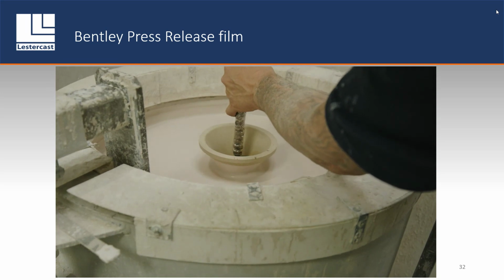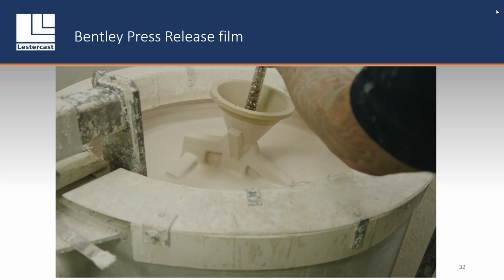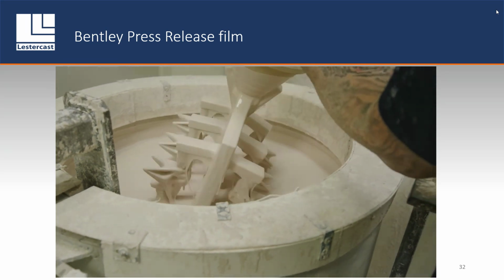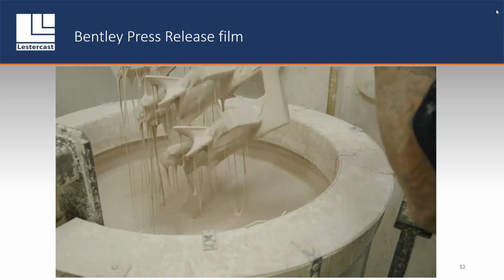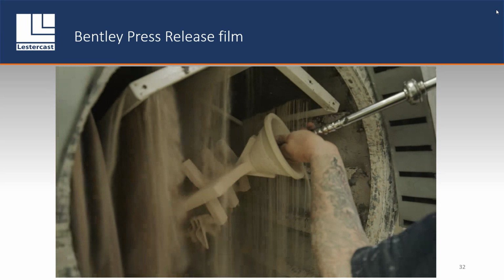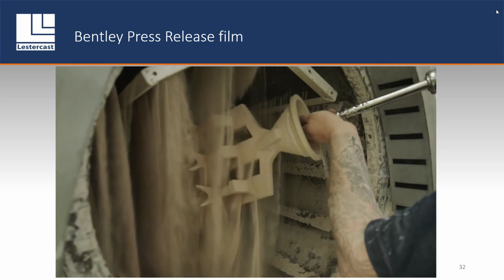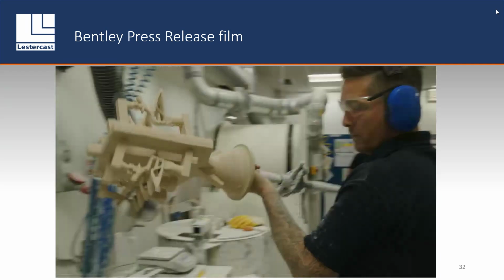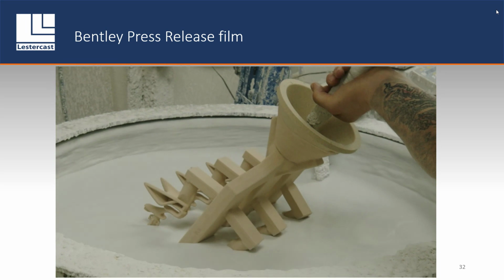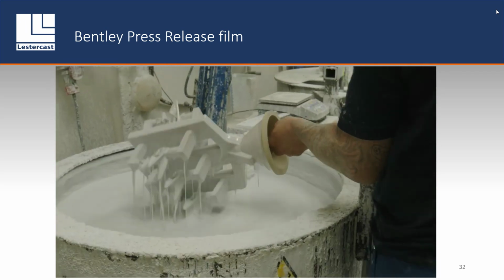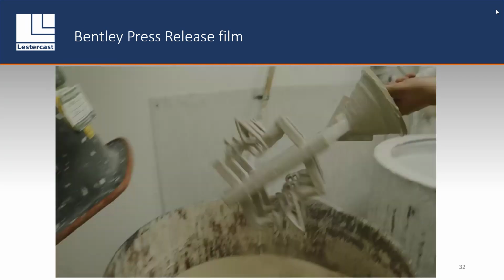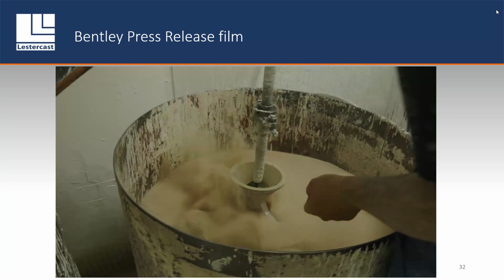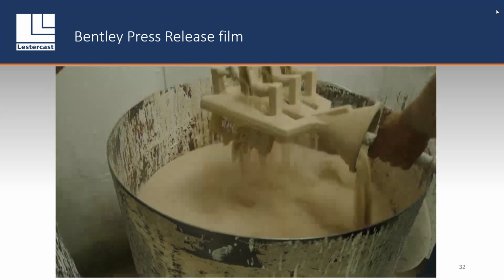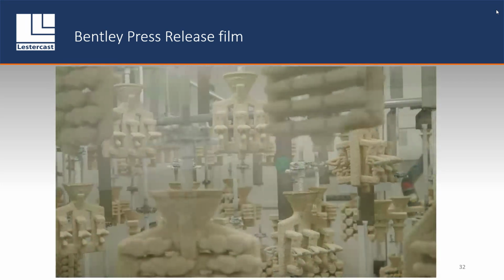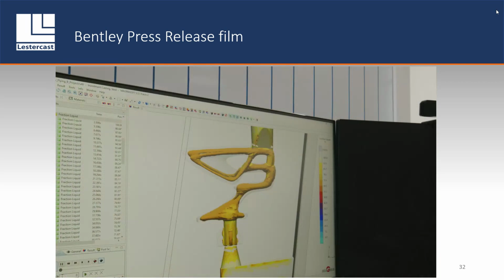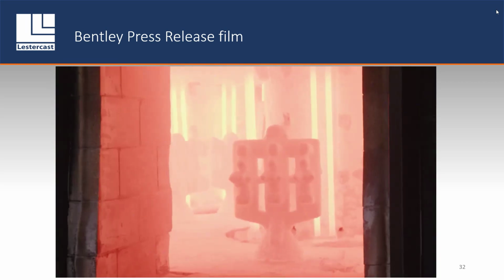So this is a zircon slurry-based material. That is in slow motion. So we're looking for full coverage over the wax, allow drain, remove any runs, and then we dust that under zircon sand under a rain cabinet. Once that coat's dried, we then go with the backup material, which is a mullite mineral that's used. Different type of slurry. We are all water-based slurries now. We changed over from alcohol-based materials in 2018. So we are all water-based. And after each coat, they go into a controlled atmosphere, humidity controlled, temperature controlled, with a lot of wind movement. And that's just Russell.